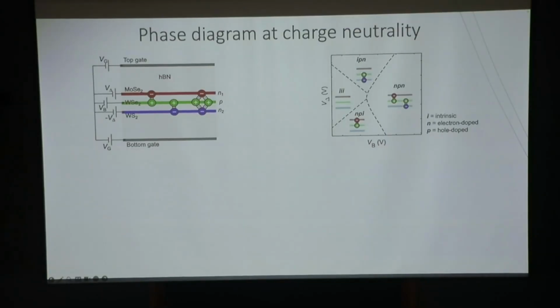So this is a phase diagram that we expect. If you increase the bias voltage, you just add more and more excitons in the system. And when you vary this vertical field, you will prefer one type of dipole versus the other type of dipole. So you can change the balance between these two dipolar excitons.